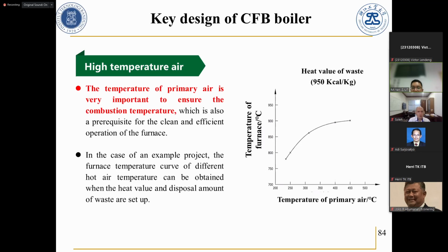And another, in the last class I mentioned, the heat value of raw waste and the heat value of feed waste are different. After we store it 7 days in a tipping hall, the heat value can increase from 1,500 to 2,000 kcal per kilogram. That means the quality of waste is well improved.